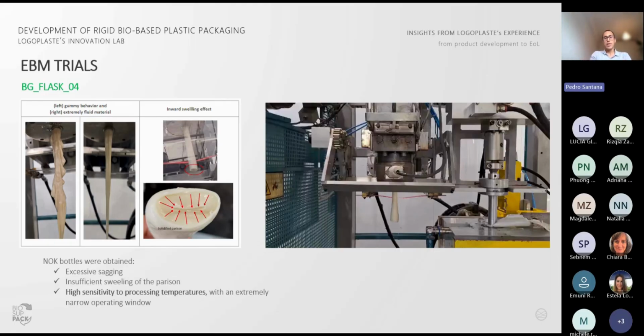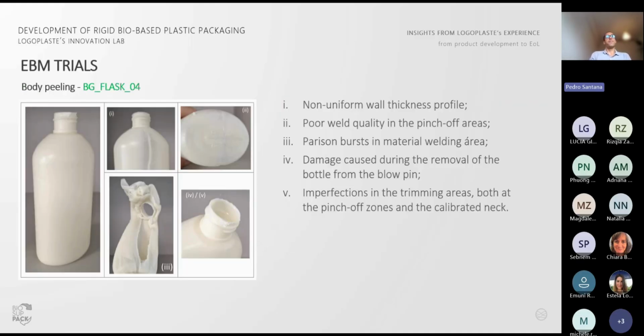Nevertheless, it was possible to produce a few packaging samples for the cosmetic case studies, although these were not considered viable due to the visual and functional defects that affected their overall quality. As you can see, the defects observed in the packages produced with the second material can be summarized across several critical points. There was a lack of uniformity in material distribution along the bottle, with thickness variations that compromise structural consistency. In addition, poor adhesion was detected in the pinch-off and trimming areas, which could affect both the seal integrity and overall finish of the package.